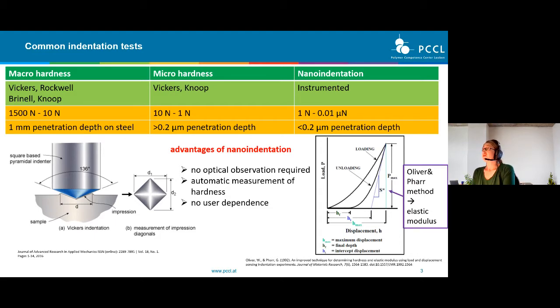Nanoindentation is an instrumented indentation. And here we have the advantages that there is no optical observation required. We have automatic measurement of hardness, and there is no user dependence. We are working in force regimes of 1 Newton down to 0.01 micronewton. And we have very shallow indentation depths, which are smaller than 0.2 micrometers. Here on the right side, you can see a typical force penetration curve of nanoindentation. We have a loading phase where the force is going up, and then an unloading phase where the force is going down. And from this unloading phase, we can also get the elastic modulus by the method of Oliver and Pharr.